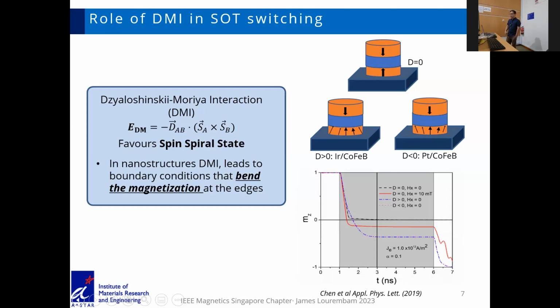some years ago, where you have a plot of magnetization in the Z direction, and the x-axis is basically time, with a pulse electrical current that has been passed through. So when D is equal to 0, the Mz basically goes to 0, and then once you remove the pulse, it could either be 0 or 1. But when you have a DMI, for example the red line, then once you remove the pulse, it switches to one direction.